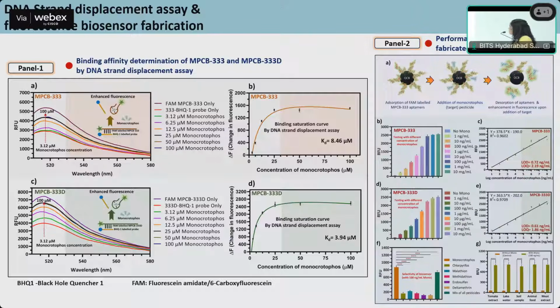Also for the KD value, you can see we utilized different concentrations of monocrotophos together with several controls. In both cases, MPCB333 had a KD of 8.46 micromolar, and MPCB333D was 3.94 micromolar. So we were quite satisfied with these results. We have done the analytical testing at various concentrations, where the MPCB333 aptamer gave us an LOD of 0.72 nanograms and the truncated one 0.61 nanograms.